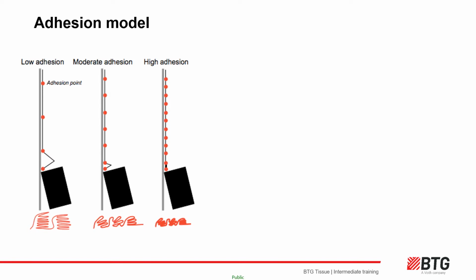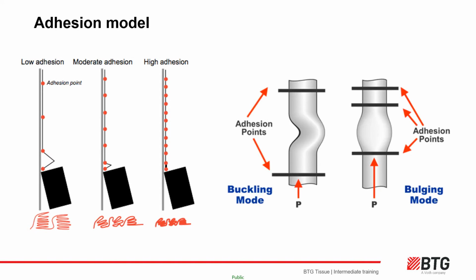You can see that low adhesion leads to a coarser crepe, higher bulk and lower softness. And high adhesion generates more crepe bars per centimetre, leading to a more densely crepe sheet, which gives higher softness and lowest bulk. The sheet is folded between adhesion points into the macrofold. At very high adhesion levels, the sheet explodes, causing bulging rather than folds.